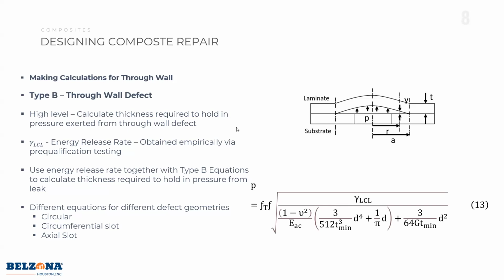So this allows us to figure out how much pressure we can hold. And it has a lot to do with the composite itself, but also the epoxy resin. You want it to stick a lot to the substrate, because if you don't have good adhesion, the fluid can escape through the ends or underneath the repair, which is what you'll see later.